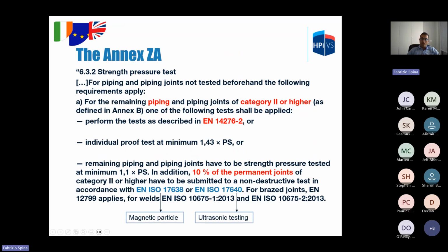So for piping, there are two different options for the strength test: the piping of category 2 and higher, and the piping of category 1 and lower, so category 1 and SEP piping. For category 2, the first point is addressed in the next slide. Individual proof test at minimum 1.43 PS is required. So these are the options for piping of category 2: perform the test as described in EN 14276 part 2, or a pressure test at 1.43 PS, or a pressure test at 1.1 PS and in addition 10% of non-destructive testing on the permanent joints. This test must be magnetic particle or ultrasonic testing.